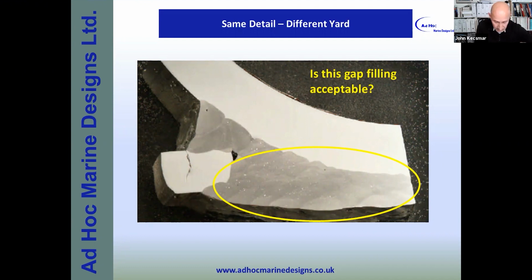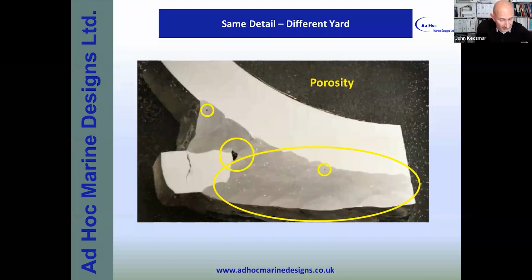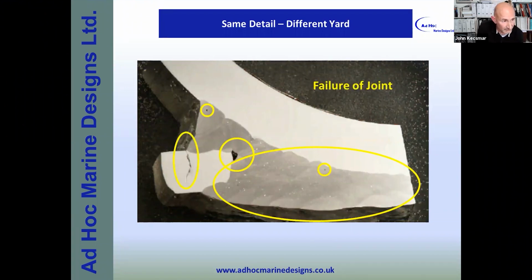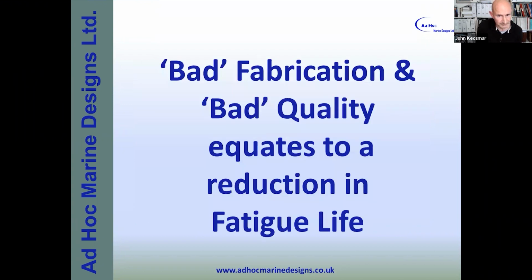Is it acceptable? Well, surprise, surprise, as we've already seen, poor quality and poor adherence to any kind of quality control, you have lack of fusion. And you can easily see the porosity. You don't need to look under a microscope. And so, surprise, surprise, it failed. And it failed with just, I think, about 2-3 weeks of service. It's appalling. So bad fabrication and bad quality equates to reduction in fatigue life.